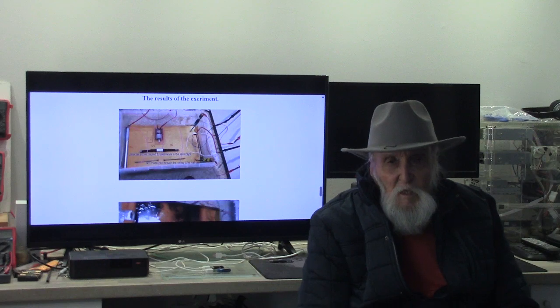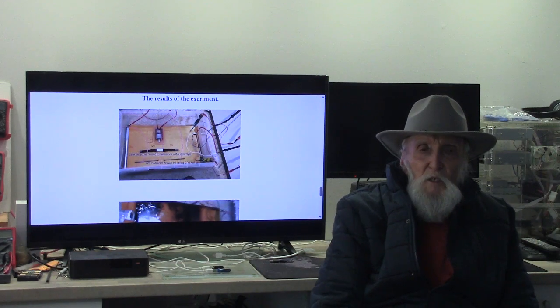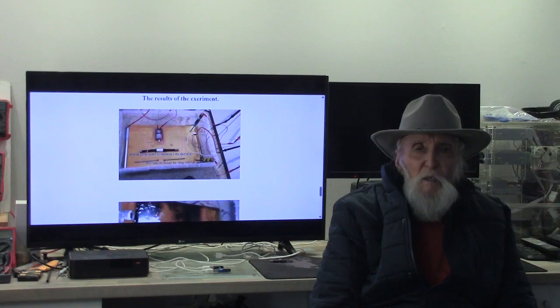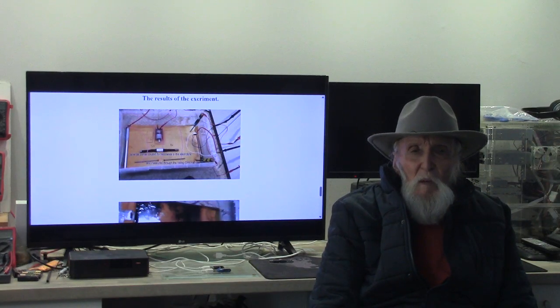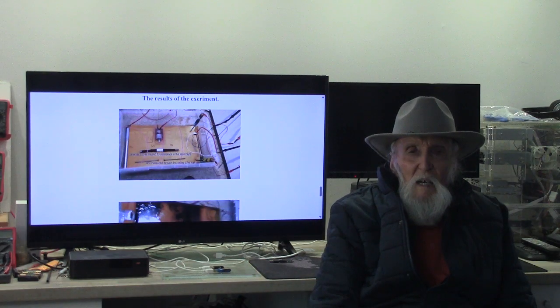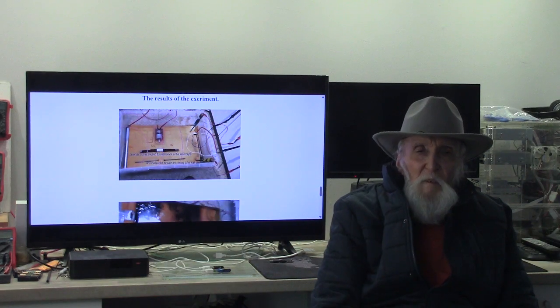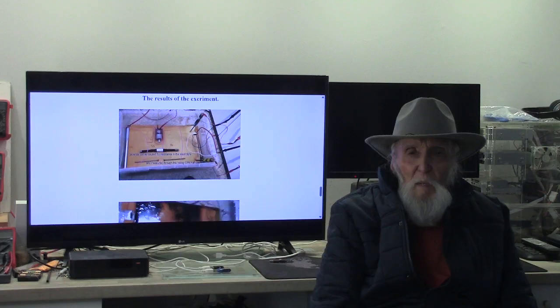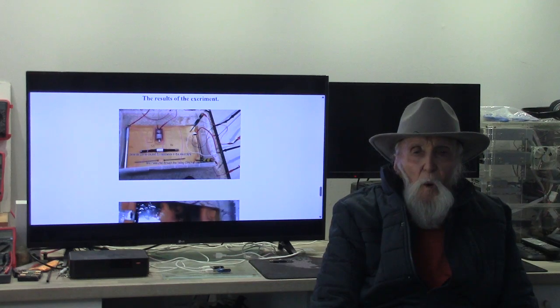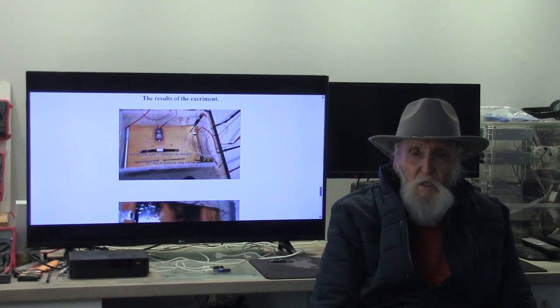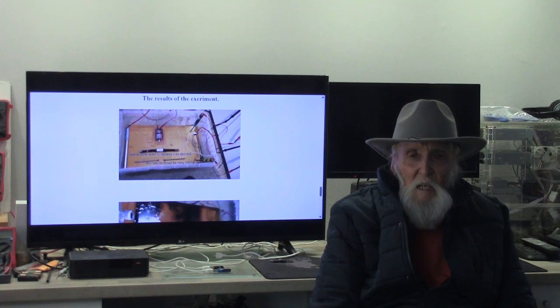This experiment conclusively demonstrates that stray current-induced corrosion is capable of producing catastrophic pipeline failure under operational conditions. When sacrificial anodes become depleted, or when stray electrical currents of higher potential enter the system, the pipeline steel becomes anodic and begins to dissolve.